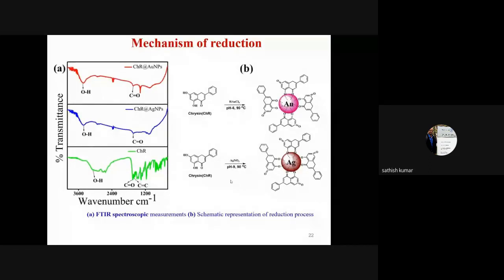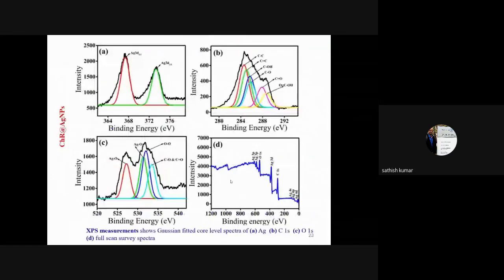At least we can predict the possible reduction mechanism involved in the reduction and stabilization of the particles. Whereas in plant mediated synthesis, we cannot predict even the possible reduction mechanism. So FTIR is a preliminary study. So we have to go for further analysis like X-ray photoelectron spectroscopy. This X-ray photoelectron spectroscopy will give information about the elemental composition of the nanoparticle.